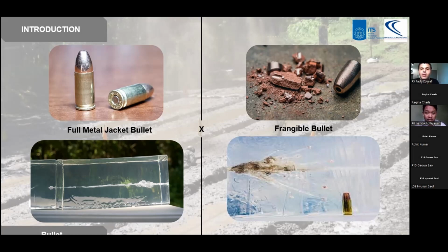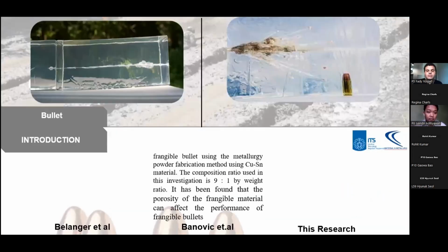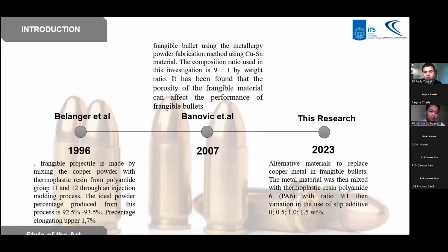This figure explains how the full metal jacket or conventional bullet passes the gelatin test, and the frangible bullet, you can see, has a different path, like in the human body. The research from Belanger et al.: frangible material is made by mixing copper powder with thermoplastic resin from polyamide group 11 and 12 through an injection molding process. The ideal powder percentage produced from this process is 92.5% to 93.5%, with a percentage elongation upper 1.7%.